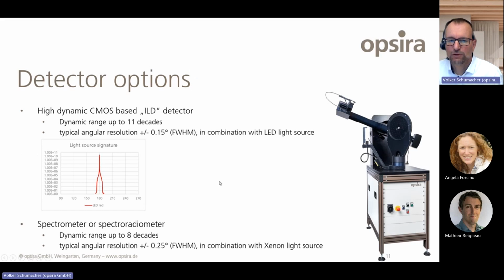In respect to the detector options, we have mainly two detectors available. There is a high dynamic CMOS-based detector. This has a dynamic range of up to 11 decades and a typical angular resolution of plus minus 0.15 degree, full width half maximum in combination with an LED light source. Here we see the signature of the machine. We go up from 0 to 11 decades. This is a logarithmic scaling, what we see here. And here we have a very narrow full width half maximum characteristic.